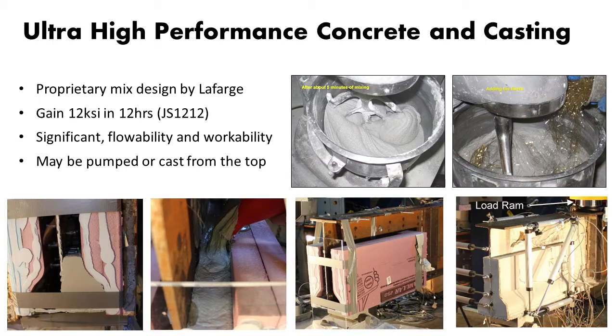This shows quickly how we made the form. Very simple. We used isolation form. We had a plexiglass window in here to see how the concrete fills. And we simply poured concrete from the top, but it can be easily pumped if there is a complex geometry. And ultra-high performance concrete has a matrix and also high strength fibers. We use a proprietary mix by Lafarge, and this mix can gain 12 ksi strength in 12 hours. So you indeed can be done with this repair in 1 day or, let's say, 2 days. And as I said, it's very flowable, almost liquid.